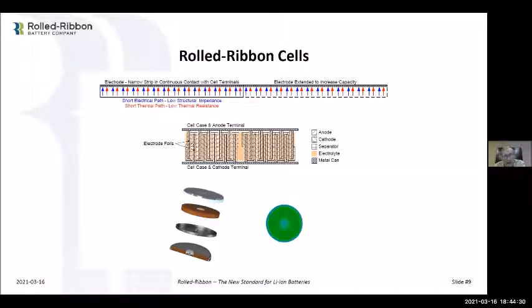Now, the way we put that together, you look at this diagram here, so we have the electrode foils here, and you'll notice one of them comes in contact with one pan, the anode pan, the other one comes in contact with the cathode pan. And then there's a separator, what we call a Z-fold, in between the two, so that the electrodes don't short out. There's a separator in the other cells too, but they rely on the tab to get it out. Our tab is the edge. And so we counterpoise these with a Z-fold. The Z-fold ensures that the anode and cathode edges never touch the opposing pan. And so we wind this up in that Z-fold.